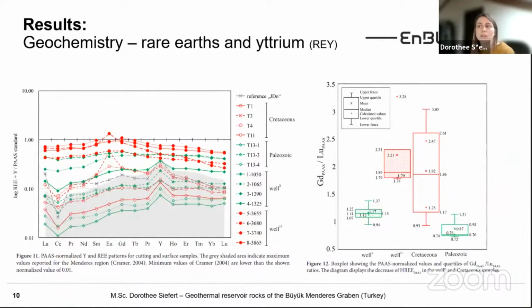So to come to the rare earth elements, here they are normalized to the PAAS standard. Compared to the Cretaceous samples, the Paleozoic samples tend to have slightly lower rare earth contents, but in general they lie within the range of the Menderes region according to literature, with a negative cerium and a positive yttrium anomaly. And within the Cretaceous samples, each sample also shows a negative cerium and a positive yttrium anomaly. So the well samples show generally higher absolute, and also normalized, rare earth element values in comparison to the surface samples.